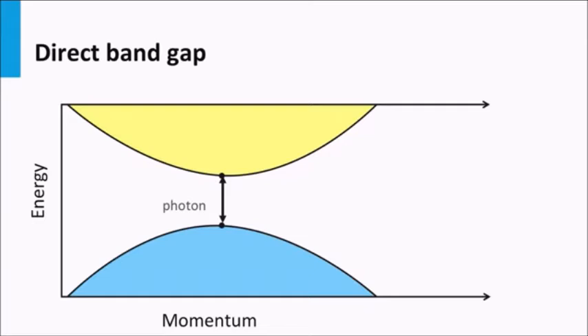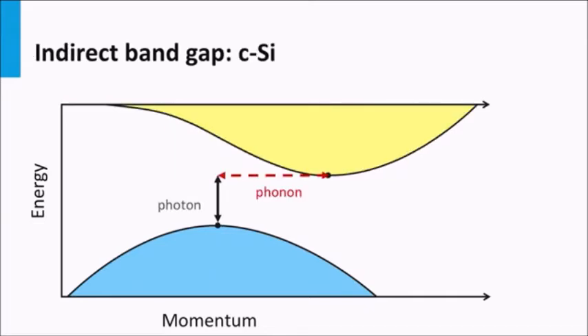This means that the excitation of an electron induced by photon absorption is more likely to happen for direct bandgap materials than for indirect bandgap materials. For direct bandgap materials, no additional matching momentum coming from phonons has to be delivered. Or in other words, the absorption coefficient for direct bandgap materials is significantly higher than for indirect bandgap materials. The same concept makes the reverse process of radiative recombination more likely to happen in a direct bandgap material. In an indirect bandgap material, additional momentum is required to make the electron and hole recombine.